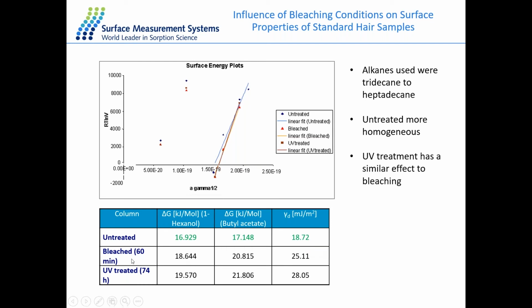However, when we start to bleach the hair or treat it with UV, you get quite a higher dispersive surface energy. So this indicates introducing a bit more heterogeneity to the surface of the sample, which is what you would expect if we are treating hair with quite harsh conditions. We can also understand the free energy between the samples and hexanol and butyl acetate. And again, what we can see is that we have a smaller interaction with our untreated sample and a higher interaction with our bleached and UV treated samples.